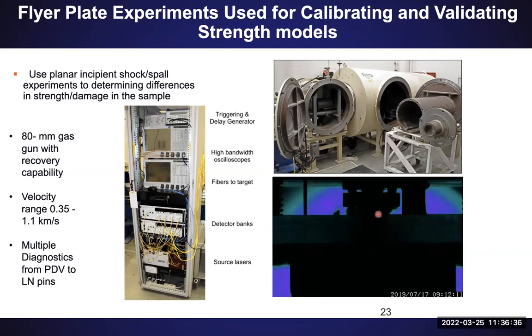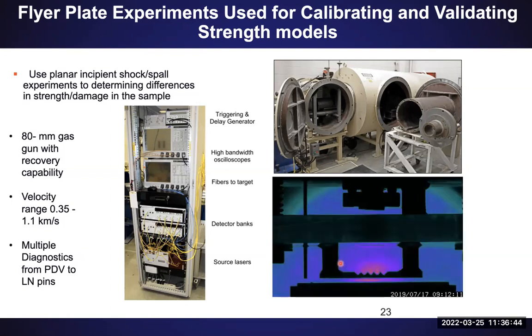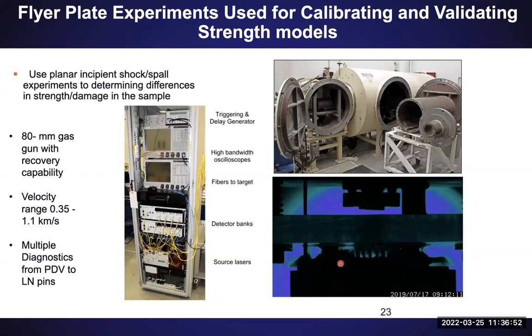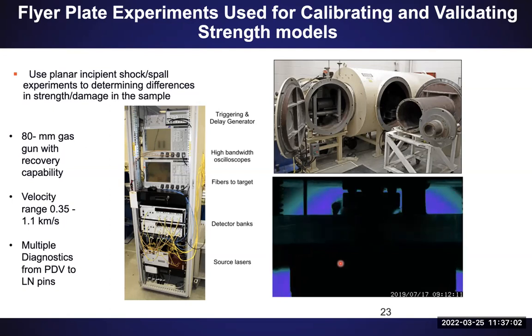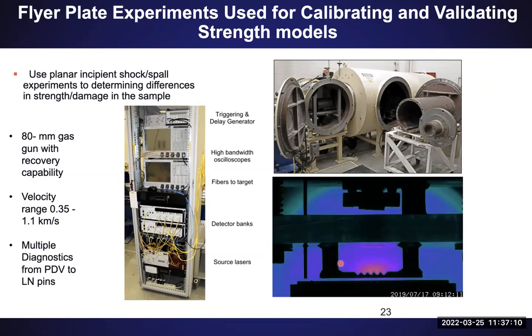On the bottom was a GIF that was playing. And this is just one of the gas guns that we have at LANL. We have 2 other gas guns within my team that we use. These facilities let us accelerate samples starting at 350 meters per second velocity up to 1100 meters per second. We can basically change this velocity, and depending on the experimental setup, we can estimate what the peak stress is. So we basically say, I want to load the sample at like 2 GPa, and we determine all these experimental parameters.